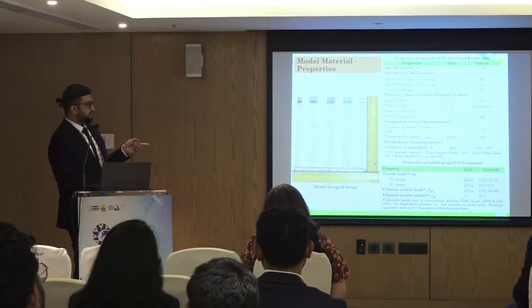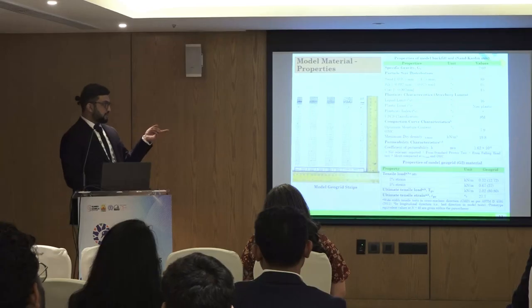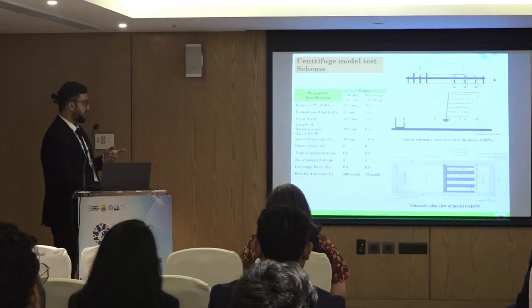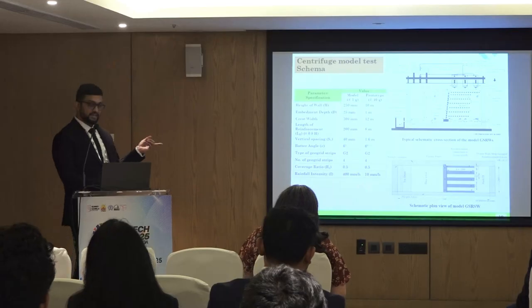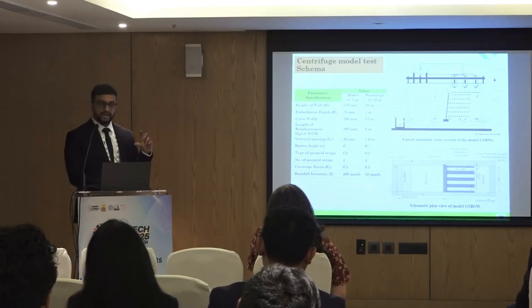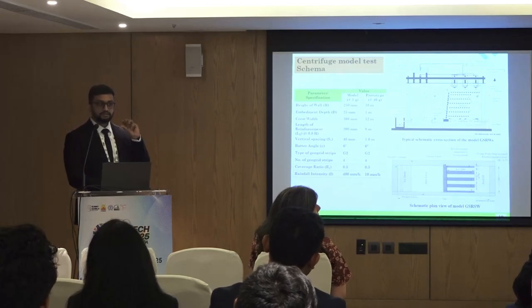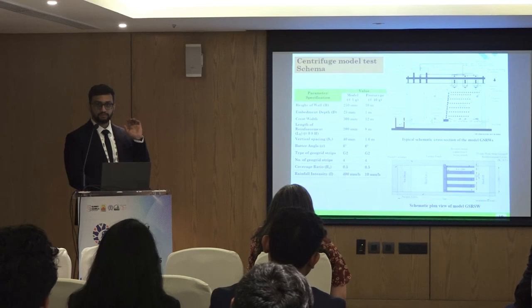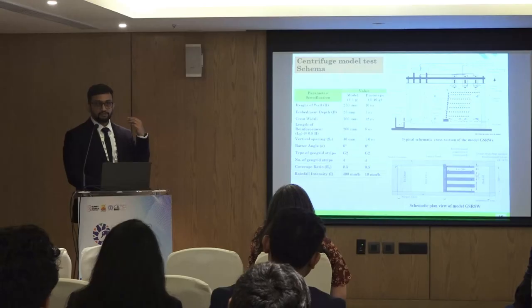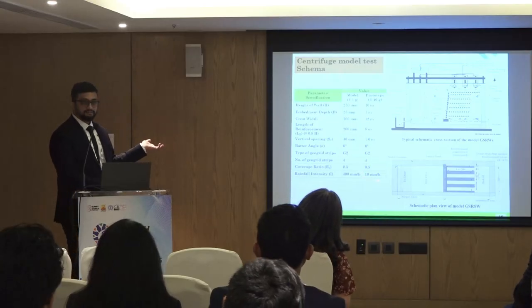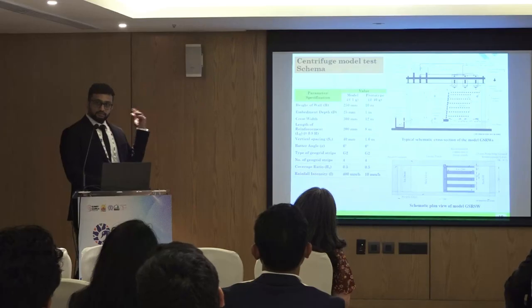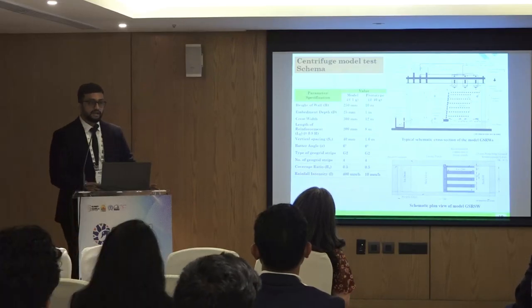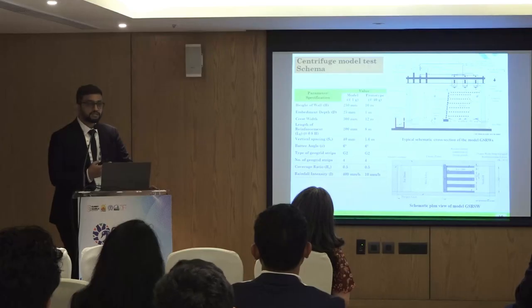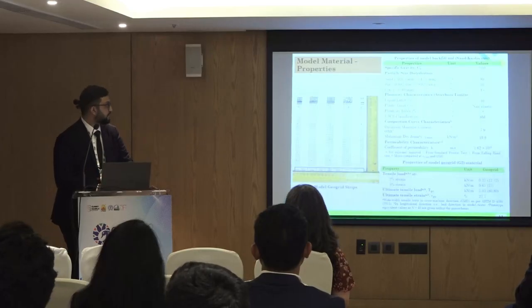And when we were finding out the permeability characteristics, it's at 10 power minus 6, and the rainfall intensity is about 10 mm per hour. There is a parameter called I by Ks, which defines whether the rainfall is being infiltrated or transferred into runoff. We want the effect of infiltration rather than runoff. So that's another reason why we targeted 10 mm per hour. Previous tests were done with higher intensity, but eventually most of it was runoff. It was not infiltrated into the body.